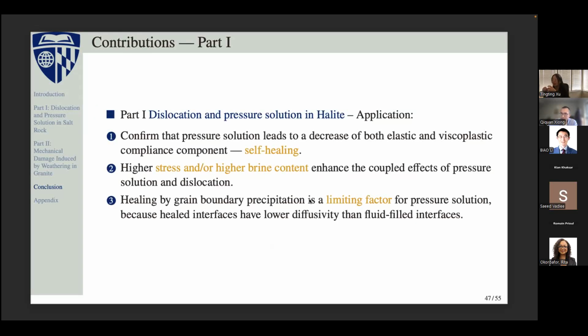And I have a little bit of a summary of the contributions of the halite model. In terms of the application, we see that the model can capture the self-healing mechanism, and it can also explain why the grain-to-grain contact healing is a limiting factor of the pressure solution mechanisms, and how all these limiting factors influence the overall response that we observed in the laboratory.